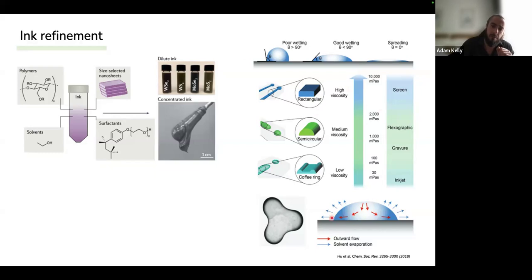So as the droplets evaporate at the contact line here at the edges, anything that's contained within the droplet itself will tend to migrate towards the edges. So this is known as the coffee ring effect. And you don't want this because you don't want all your active material just at the outside of the droplet. What you would like is a continuous network where it's homogeneously deposited. So this is a problem that you need to monitor by using things like binary solvent systems or just by